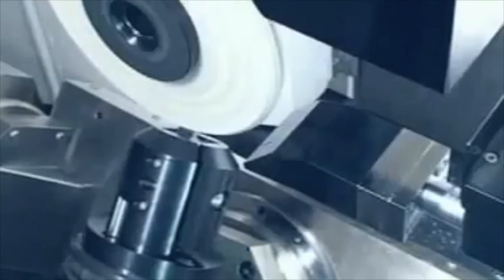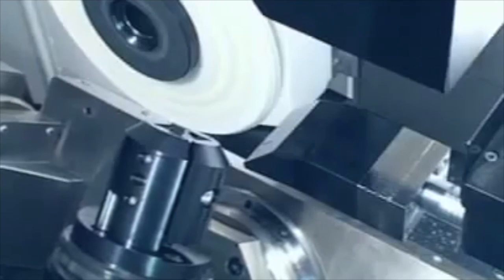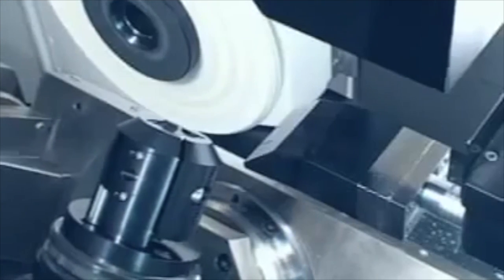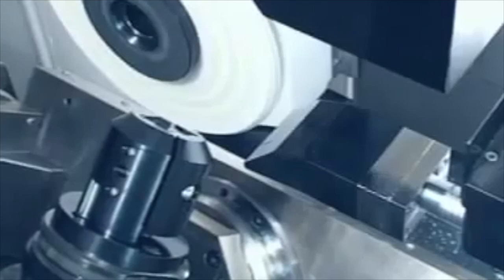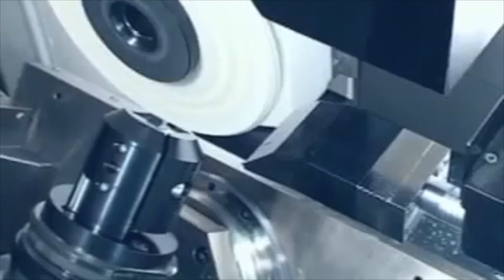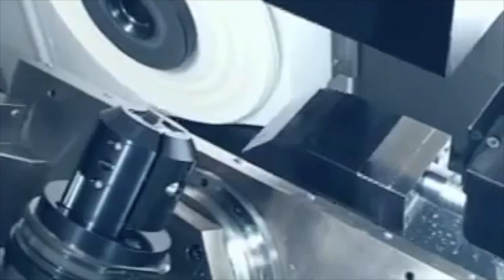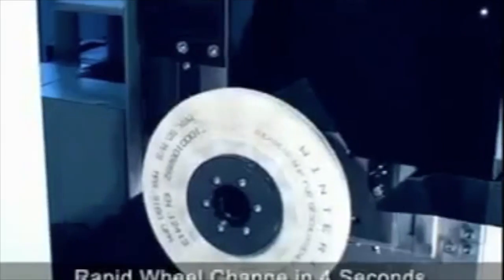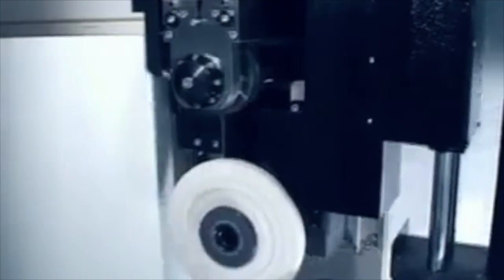The coolant helps keep the workpiece and the grinding wheel cool so the material is not burnt. In addition, the coolant transfers away the swarf material, keeping it from fouling the wheel. If the wheel becomes clogged up with the substrate material, the effective cutting edges of the abrasive are dramatically reduced. Once the wheel is clogged, the part manufacturer needs to redress the wheel and expose newer, sharp abrasive crystals to re-establish the profile geometry on the grinding wheel.